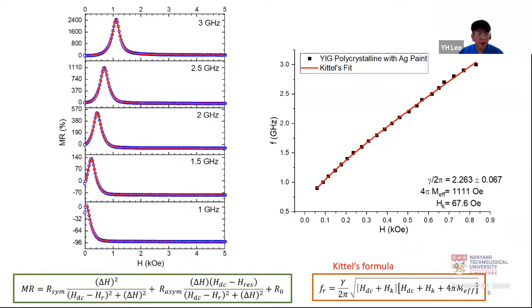On the left-hand panel, we only show 5 frequencies, namely 1 to 3 gigahertz in multiples of 0.5. We can see that the curve fits very nicely. From the Lorentzian fitting function in the green box at the bottom left, we extract 2 different parameters, namely the resonance critical field HR and delta H, the line width. Using the HR values, we plot frequency versus the HR critical field on the right-hand side, and fit it with the Kittel expression for the in-plane ferromagnetic resonance equation, as shown on the bottom right.